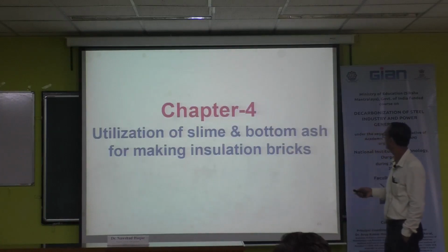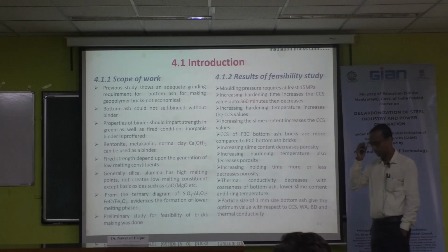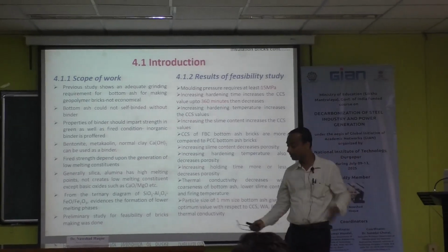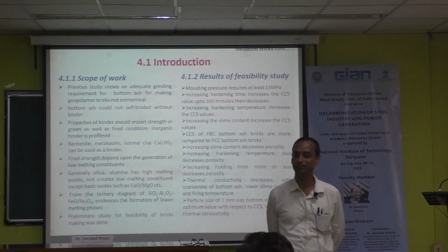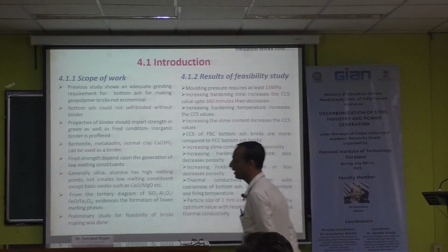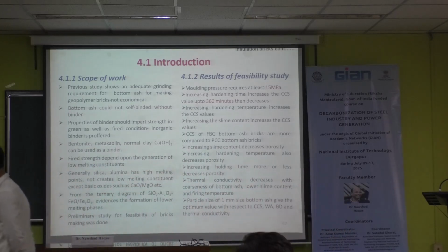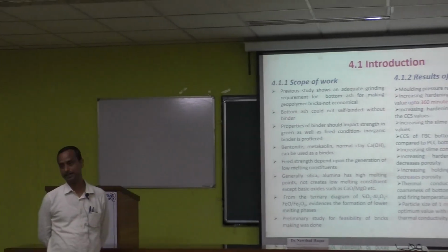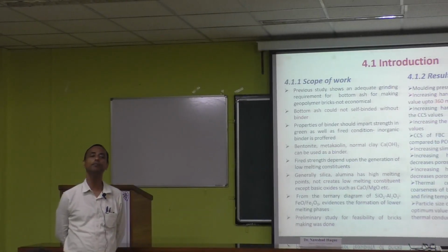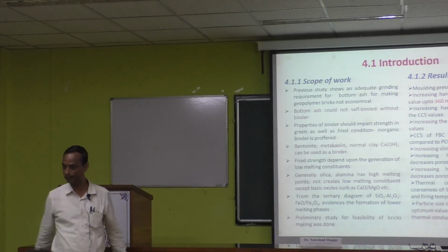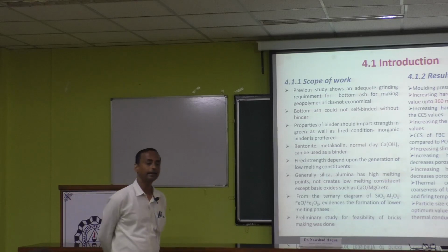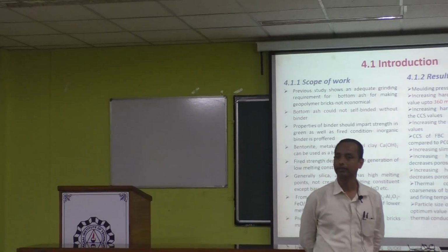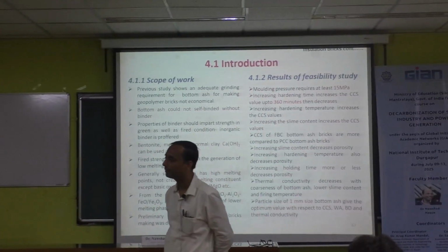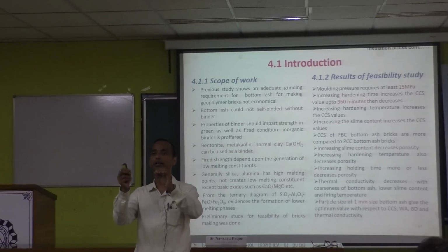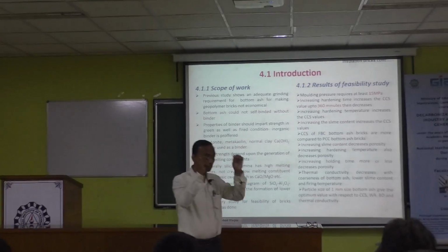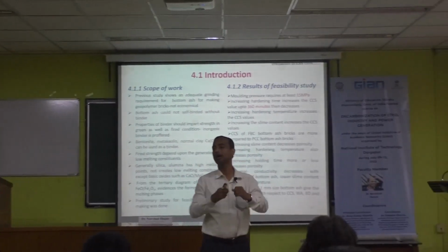Then we tested it as an insulation. The driving force for insulation is this: when we characterized the iron ore slime and bottom ash, we observed that the iron ore slime should have some binding strength and bonding property. Clay we generally use for binding purpose. And bottom ash is a porous material. Porous material generally has high interparticle space, and when the materials are porous in nature, the interparticle space will be big.